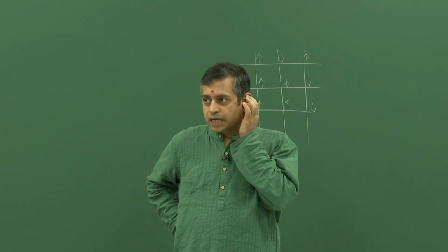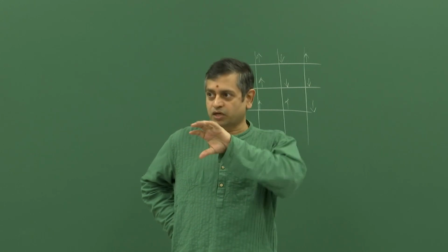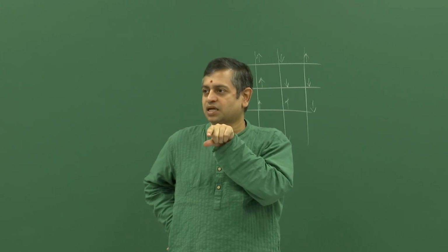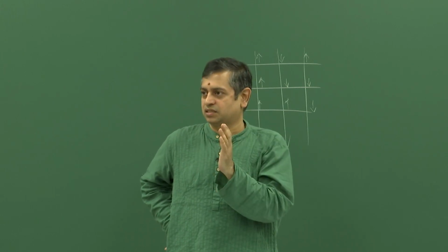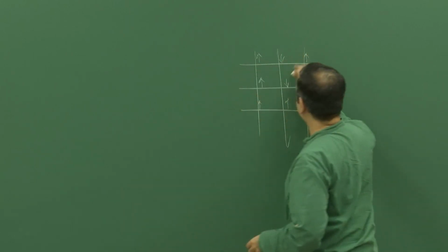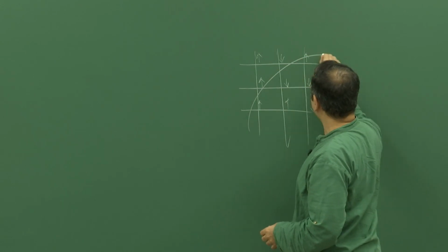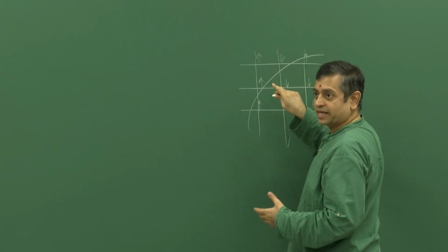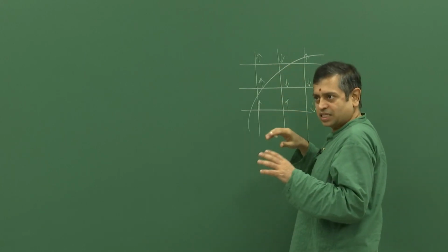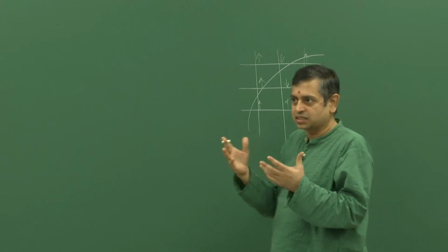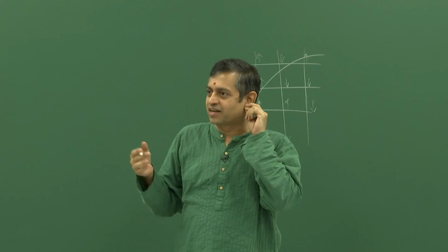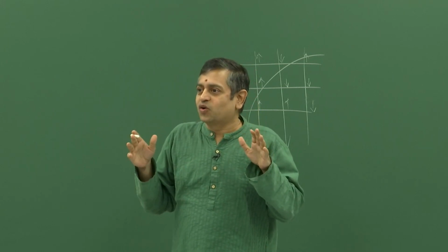Yeah, in this microstructure evolution book, Mirzadeh shows how this rule about unlike neighbors actually captures at some level the information about the curvature, which is probably not difficult for you to see, right. If I have one like this, if this is curved like this, then these points will have unlike neighbors, right. If it is flat like that, it will have some number of unlike neighbors. So, that is what is capturing the physics to that extent, and this model also has the mobility rigged, for example, but there is really no grain boundary.